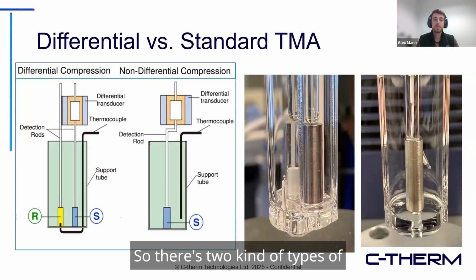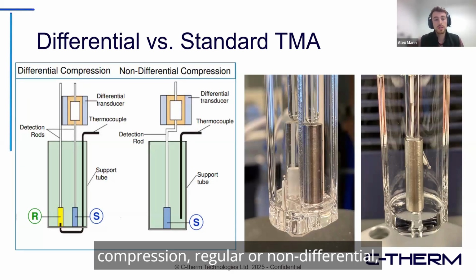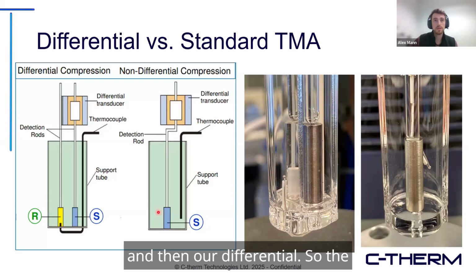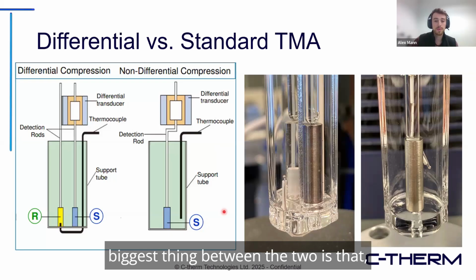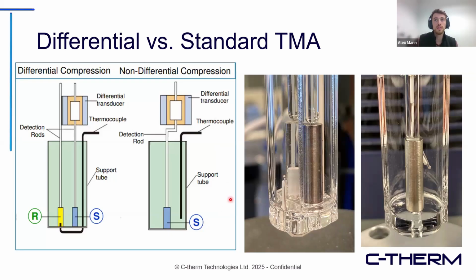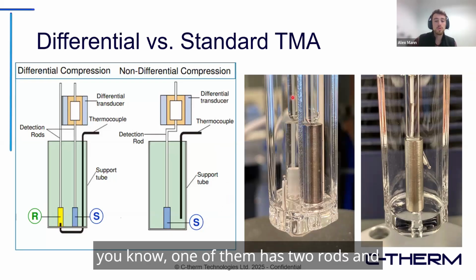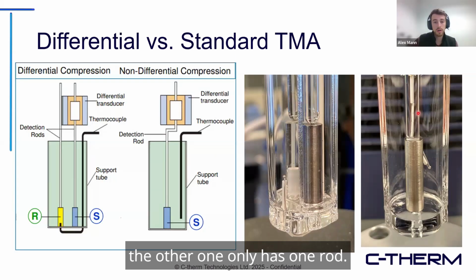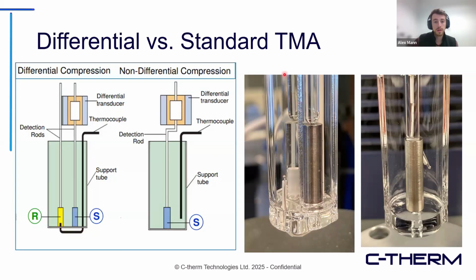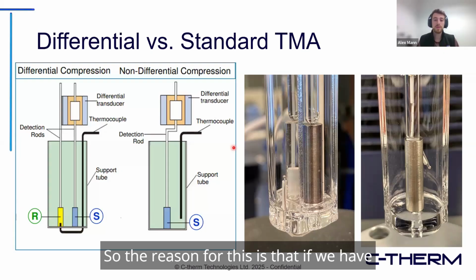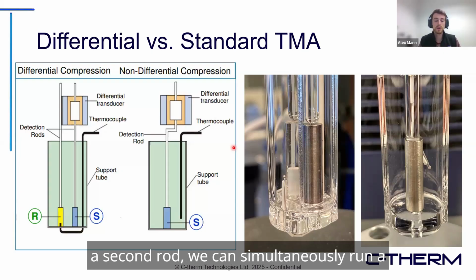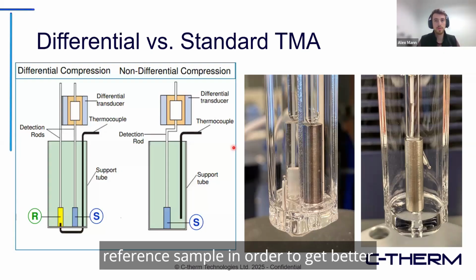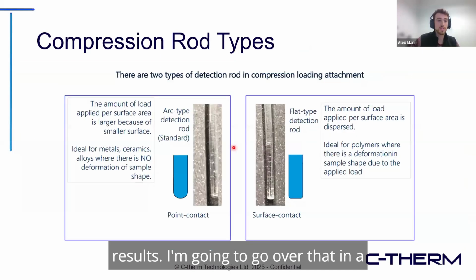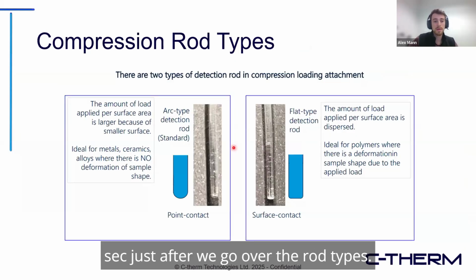There are two types of compression TMA: regular or non-differential, and differential. The biggest difference between the two is that one has two rods and the other has only one rod. The reason for this is that with a second rod, we can simultaneously run a reference sample in order to get better results. I'm going to go over that in a sec, just after we go over the rod types.